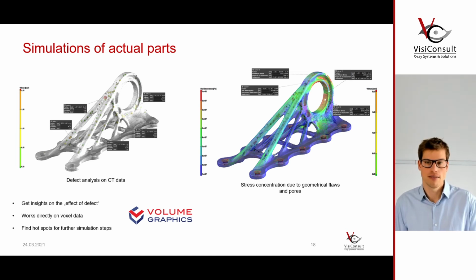So this is theoretical. But once you obtain the CT scan, where you have a real digital twin of the part with all the defects, deviations, whatever you have inside, you have a digital twin of the manufactured parts. So why not perform cyclic loading simulations, FEM simulations, stress simulations on that digital twin and actually understand what impact the defect or the geometric deviation has? And that is a great tool to gain more insights about your part and perform a more realistic simulation.